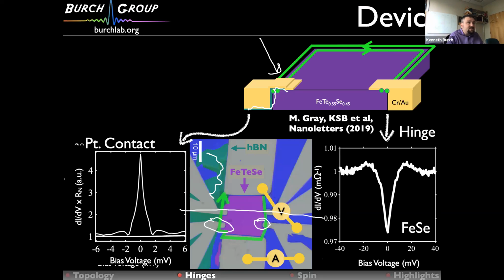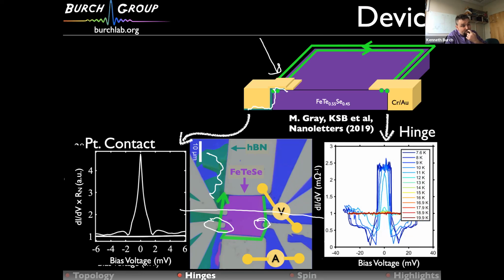And something that I'm quite excited about, which is a very recent development, is we rewired our cryostat so we could get a bit colder on the device. And also we got better crystals. And we now see something even more beautiful, which is that not only do we see the zero bias peak, we see what looks like perfect Andreev reflection. So we see this kind of flat top that's happening at these low biases, and we think it is coming from the fact that we're really tunneling into these chiral edge states of the system. But that's a very new development, so I wouldn't show it to you if we hadn't repeated it in multiple devices, but we don't fully understand it.